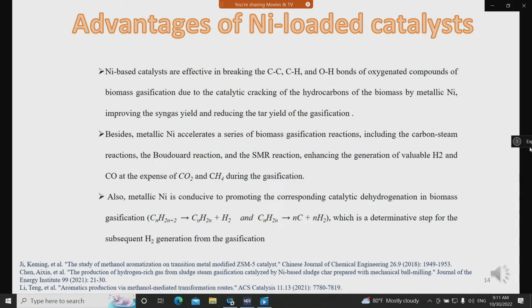Nickel-based catalysts are effective in breaking the carbon-carbon bond, carbon-hydrogen bond, and oxygen-hydrogen bonds of oxygenated compounds of biomass gasification. Also, metallic nickel accelerates a series of biomass gasification reactions. And metallic nickel is conducive to promote the corresponding catalytic dehydrogenation in biomass gasification.